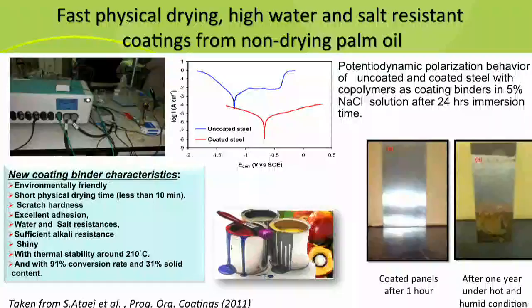If we look at our coat, we have coated this on mild steel. This is after 1 hour of coating. This is after 1 year. You can see those that have been coated will not corrode. So at least we have been successful in producing these binders.